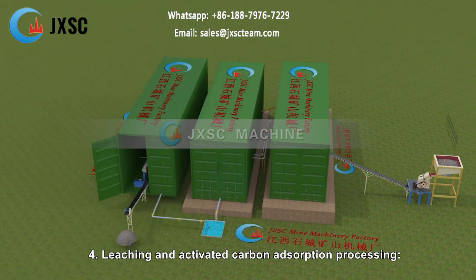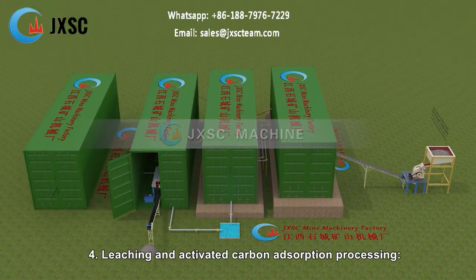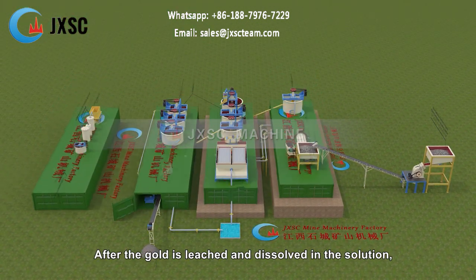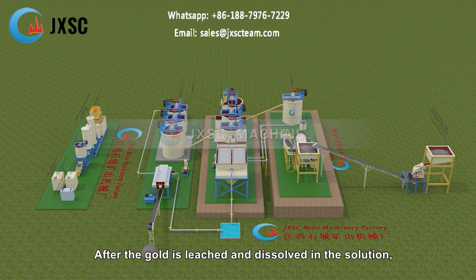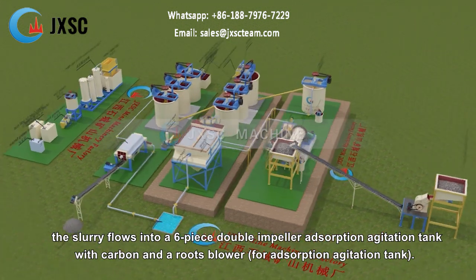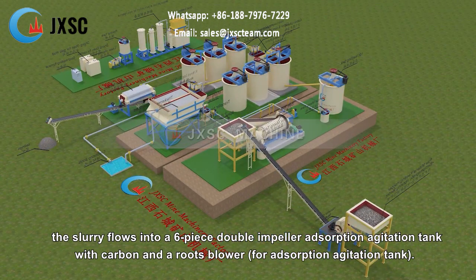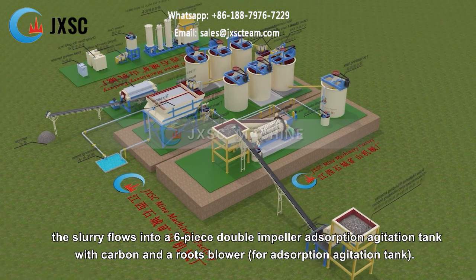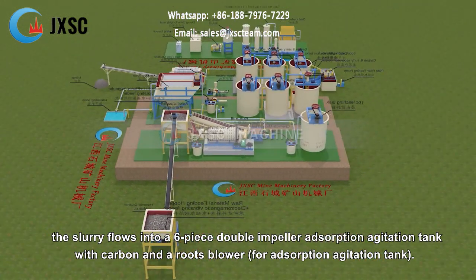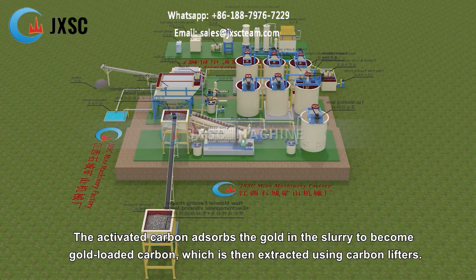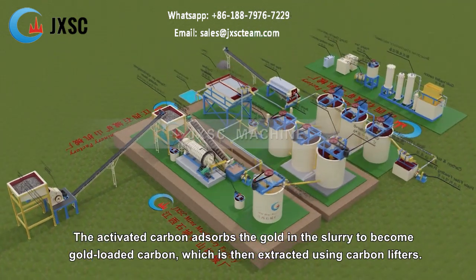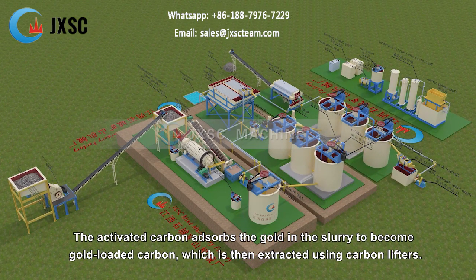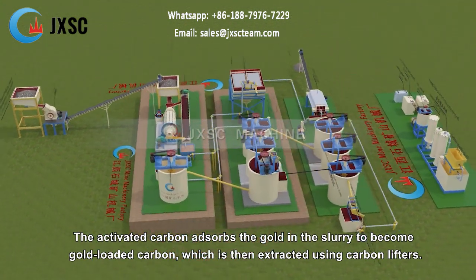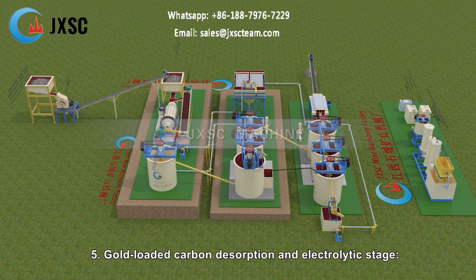4. Leaching and activated carbon adsorption processing. After the gold is leached and dissolved in the solution, the slurry flows into a 6-piece double impeller adsorption agitation tank with carbon and a roots blower. For adsorption agitation tank, the activated carbon adsorbs the gold in the slurry to become gold-loaded carbon, which is then extracted using carbon lifters.